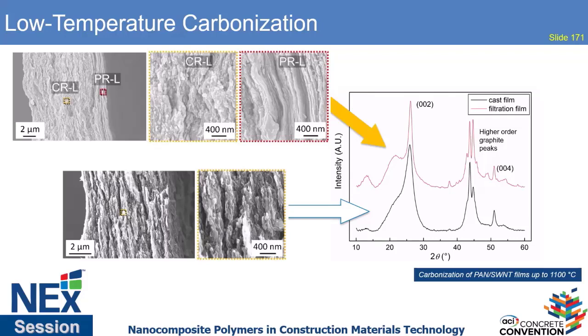So the point is that by getting this very, very nice interaction in this blended phase, it's not only having an effect on mechanical, but it's having an effect on processing of a carbonaceous structure. And if you could make graphite at 1100 degrees C, you can think about industry-wide how that would save a lot of heat in the processing. So we're working with carbon fiber producers to understand this more, because this could have a huge effect on processing. Right now you have to go upwards of 2000 degrees C to get a similar graphite structure.